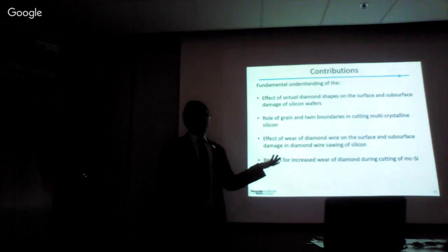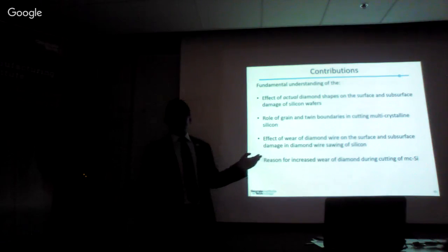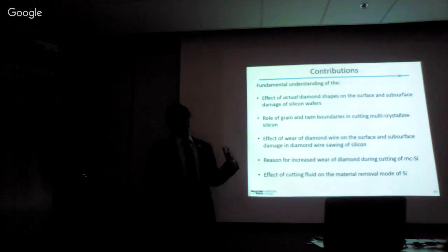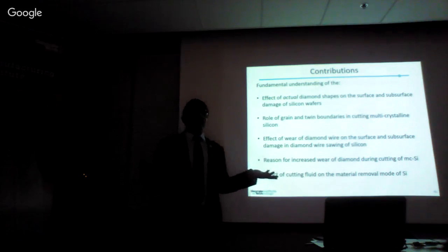We found the first reasons for the increased wear of diamond wire while cutting multi-crystalline silicon, and could explain the increased wear consumption for cutting multi-crystalline silicon versus monocrystalline silicon. And finally, I found the effect of cutting fluid to promote ductile mode material removal of silicon.